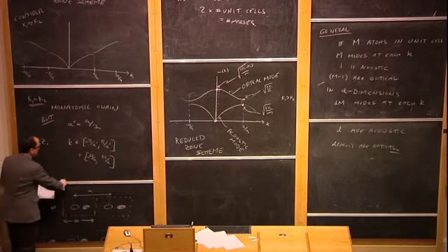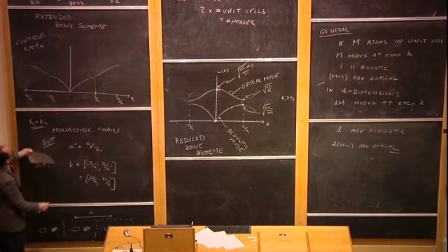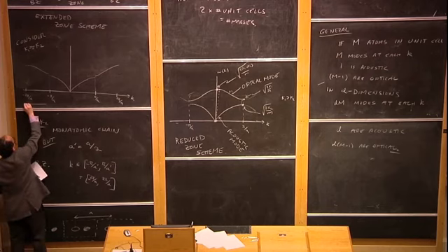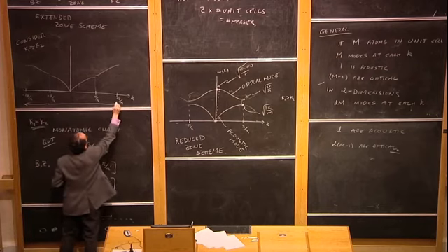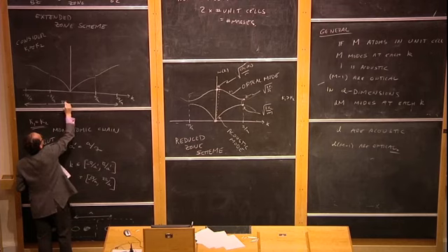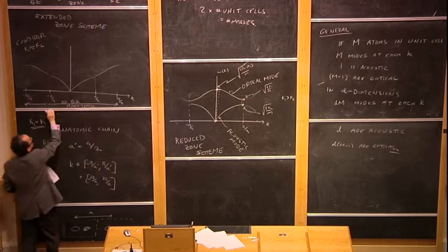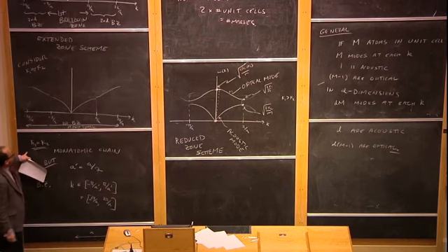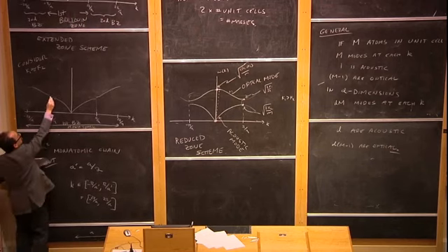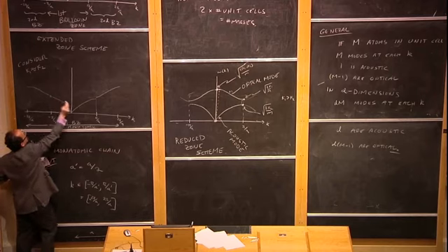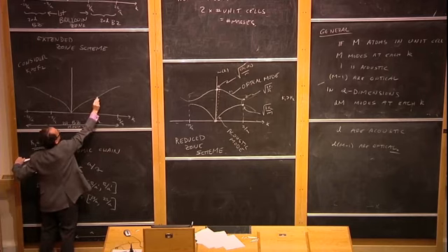So this entire range here, if the 2 masses become the same, becomes the first Brillouin zone, first BZ of the monatomic chain. And then if you make kappa 1 and kappa 2 slightly unequal, you open a small gap at the new Brillouin zone boundaries at pi over a.